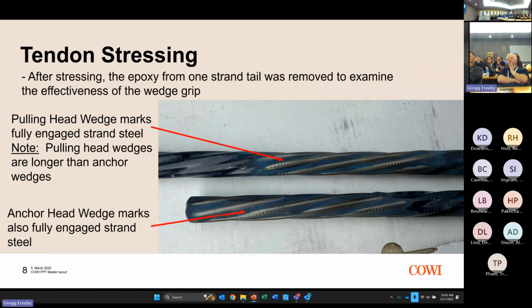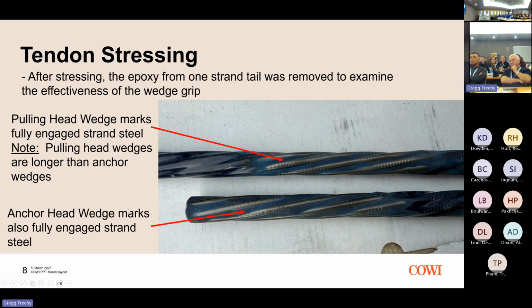So after stressing, we pulled some strand tails. One of the things we wanted to do, obviously, with this new epoxy coated system, was verify that we actually had the wedges gripping into the material. Simon also brought out a little bit thicker range on the epoxy covering over the crown versus the minimum that you see within the ASTM. And so we actually pulled some of the epoxy. You can see there that we have the pulling head wedges on the top, and the anchor head wedges on the bottom.